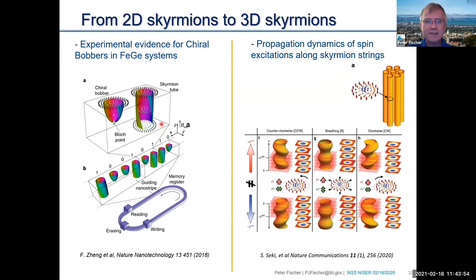This leads to studies that are really just emerging as we speak, and I think it's exciting: looking into skyrmions that really have the full 3D character. One example I want to mention is the Chiral Bobber system that the Jülich group was looking into. These are three-dimensional structures where, by applying a certain field sequence, you can generate a Bloch point. Basically, you confine the skyrmion tube that would normally go straight through the whole thickness of the stack, and it just stops at some point. And this is what this paper came up with. I really highly recommend reading it. By applying a certain magnetic field protocol, you might be able to encode the ones and the zeros, which of course you don't have the capability for in a normal two-dimensional skyrmion system.